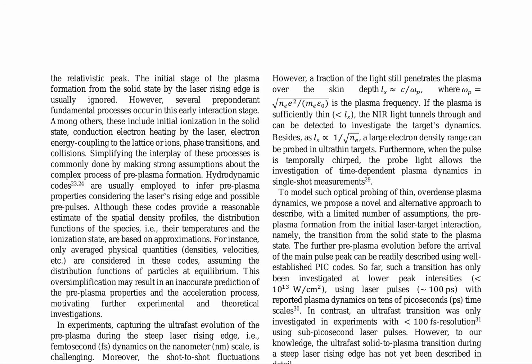Ultrafast transitions from solids to overdense and expanding plasmas are triggered by the steep rising edge of femtosecond laser pulses with peak intensities exceeding 10^16 W/cm². To investigate this phenomenon, a pump-probe approach is employed, combining single-shot near-infrared probe light transmission measurements with a two-step interaction model. The laser contrast profile, shown in Figure 1a, is accurately described by two fitting curves, essential for subsequent data analysis and modeling.